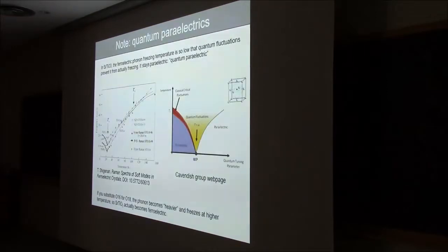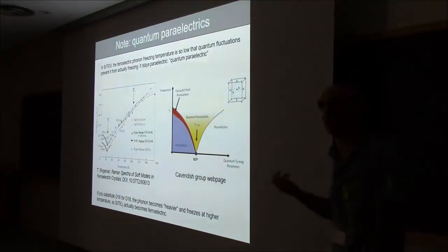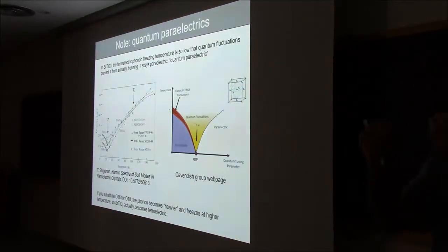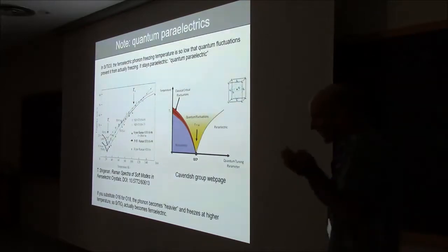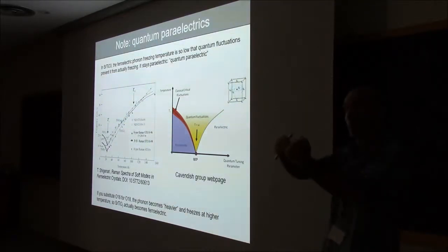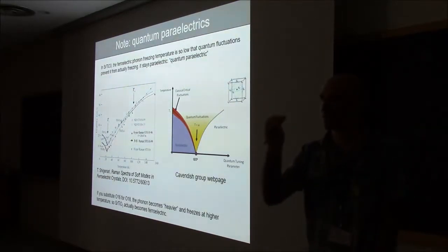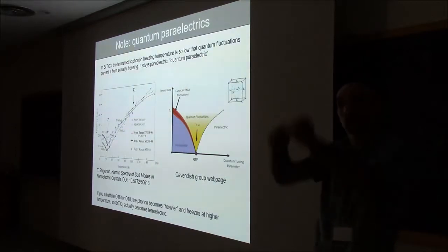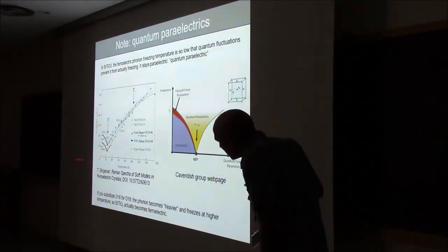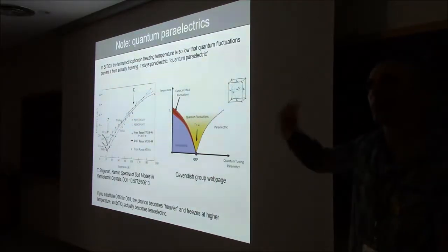One interesting thing that can happen, and this is not something that you need to know, but I find it quite exciting, so I'm going to tell you about it, is that if the phonon freezing happens at a temperature very close to 0 Kelvin, phonons have a certain momentum. If a phonon freezes, you will know at the same time its momentum, which is 0, and its position, because you know the atomic position. At 0 Kelvin, you know that quantum mechanically you cannot know exactly both things. If you multiply the phonon momentum by the position, that is basically Planck's constant. So if the phonon freezes very close to 0 Kelvin, this quantum fluctuation, this quantum indetermination, is sufficient to prevent the phonon from freezing completely.